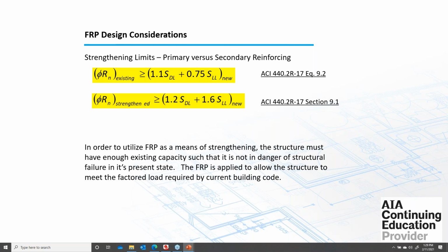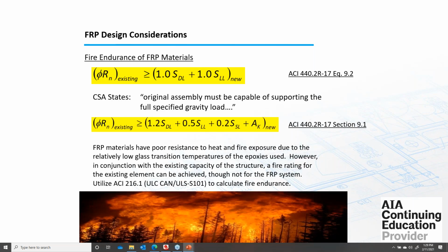But it's essentially saying that the existing structure without any strengthening has to be able to carry the service loads on its own. And then if it meets that, but it simply can't meet the 1.2 and the 1.6 safety factor loads, the ultimate loads, then that's what we're using the FRP for, to get you from the service load up to the ultimate loads. If you can't provide service loads with the existing structure and you're going to be relying on whatever system you use to strengthen it, you actually cannot use FRP. And that is particularly true in fire situations.